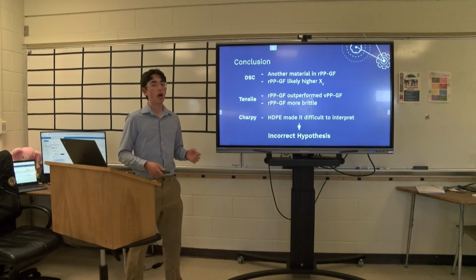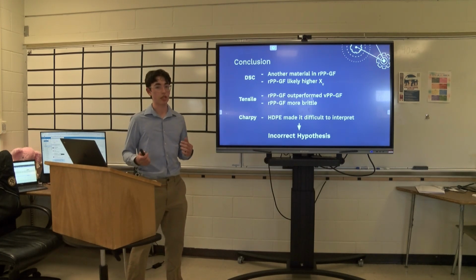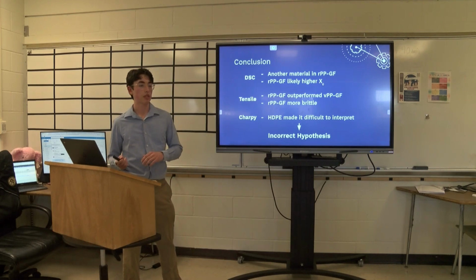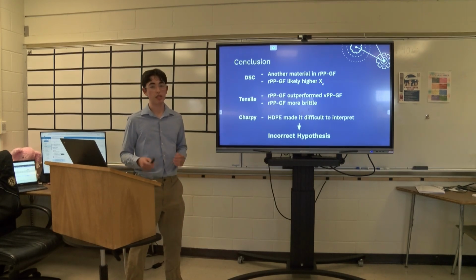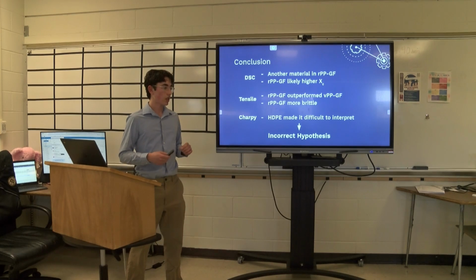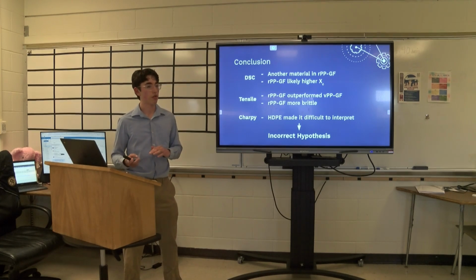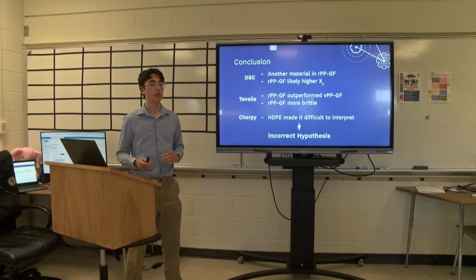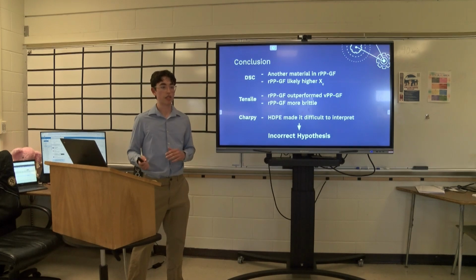And from this, we know that my initial hypothesis was incorrect. The recycled material was comparable in most cases, if not higher, in all cases. So what could the reason for this be? Well, I determined it to be likely a difference in material sourcing.